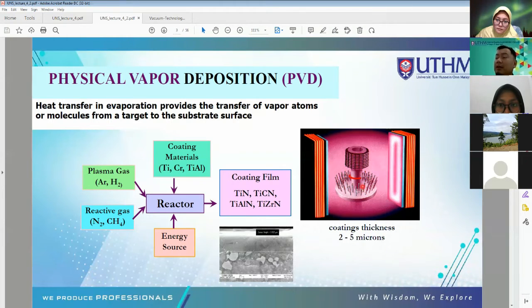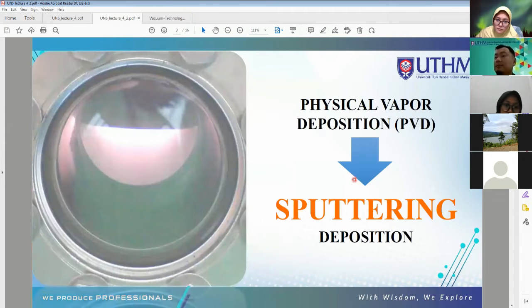So we put the drill head inside the chamber. We create the discharge of a titanium sputter source here, and then we add a nitrogen and argon environment here, so that we can create the titanium nitride coating. Most of the time, PVD is also called sputtering. Of course, there are other PVD processes like evaporation and laser ablation, but I just want to share here the sputtering deposition.